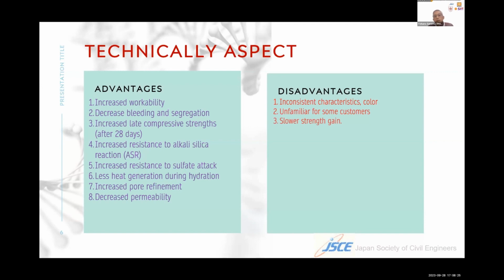So the third disadvantage is the slower strength gain. Because fly ash causes slower strength, for early strength concrete, material engineering must be carried out. For example, by adding chemical admixture. In our factory, we use type D admixture, which is the retarder, and we use the superplasticizer, and sometimes we use the accelerator.